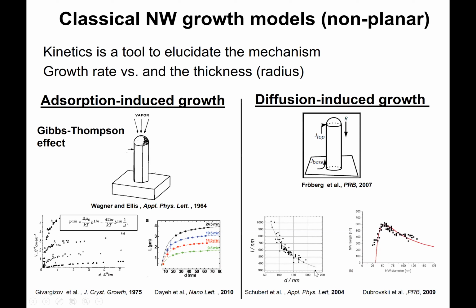But later on, during the 2000s, many cases were observed with the opposite relationship: the larger the catalyst nanoparticle, the slower the growth. And in some cases, you could even see a non-monotonic dependence, where for smaller particles, this was dominated by this Gibbs-Thomson effect.